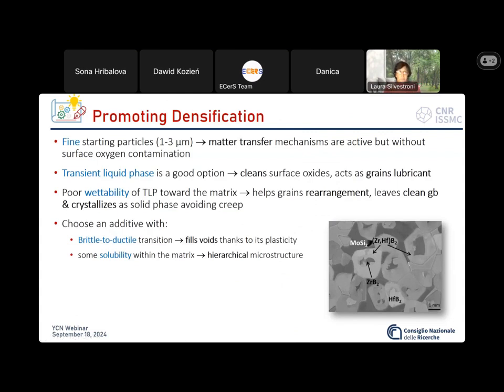So to promote the densification, the baseline is to use fine starting particles, not too fine because otherwise we introduce too much oxygen, but not too coarse so that the matter transfer mechanisms are enhanced. Then using the strategy of the transient liquid phase is a good option because at the sintering temperature we have a liquid phase that cleans the surface oxide, which hinders the densification of borides and carbides, and acts as a grain lubricant. Having a poor wettability of the transient liquid phase towards the matrix is also desired because, on one hand, it helps the grain rearrangement, but it leaves clean grain boundaries and doesn't negatively impact the mechanical properties at high temperature.